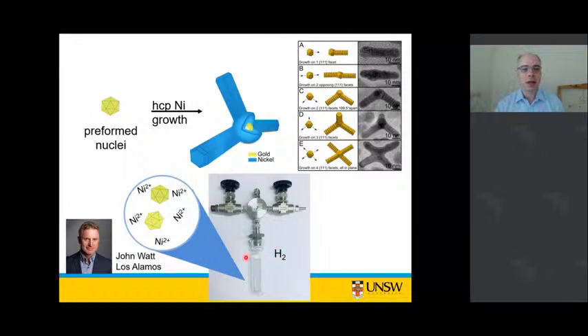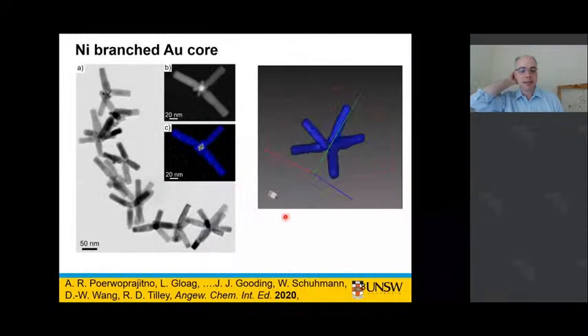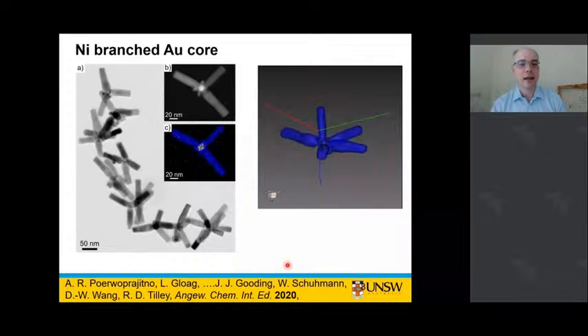So to make these branch nickel structures, and actually Agus visited one of my former students and started doing some of these experiments. So John Watt, who actually did the palladium work that I spoke about earlier, he's now got a position as a research scientist at Los Alamos in the States. So Agus went across and visited him. So to make these branch nickel structures that we were interested in, you just put in your preformed gold seed, and then you can decompose your nickel 2+ onto your gold seeds, and then end up with these branch structures. And that's exactly what Agus